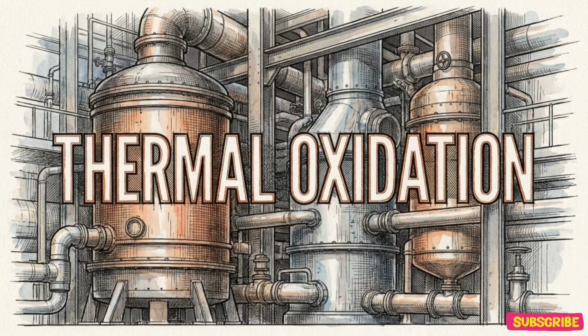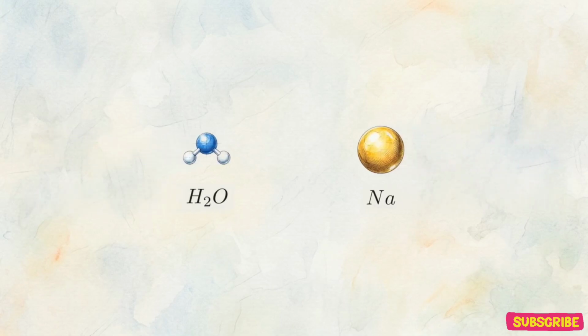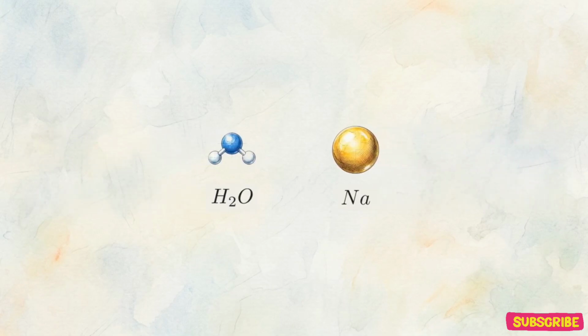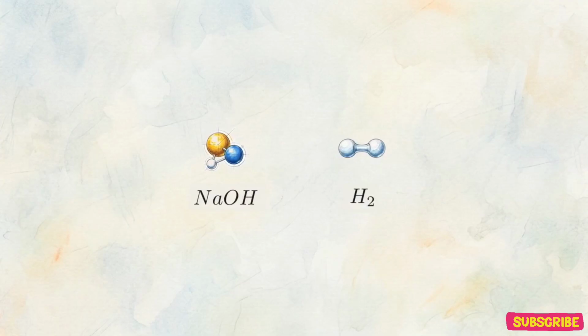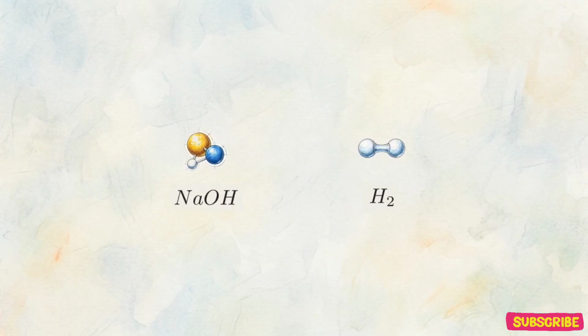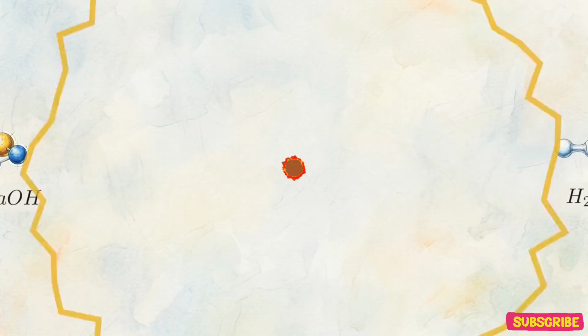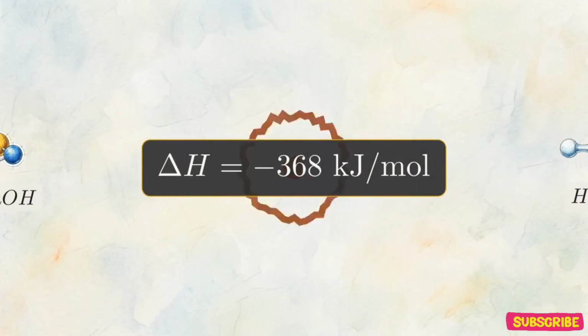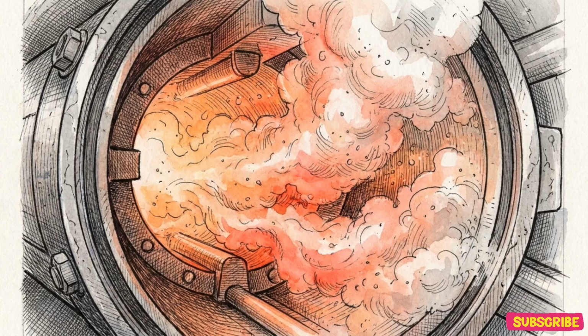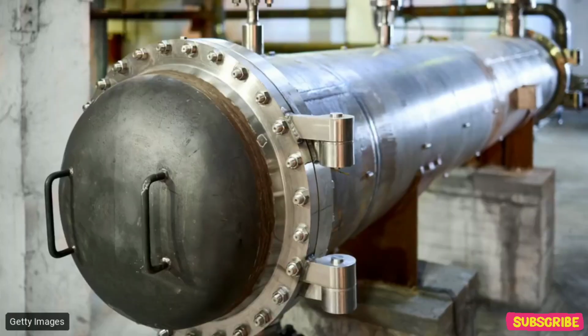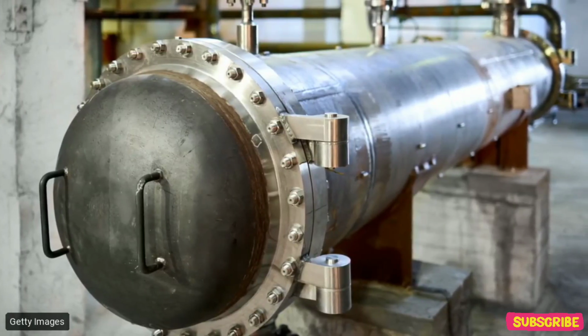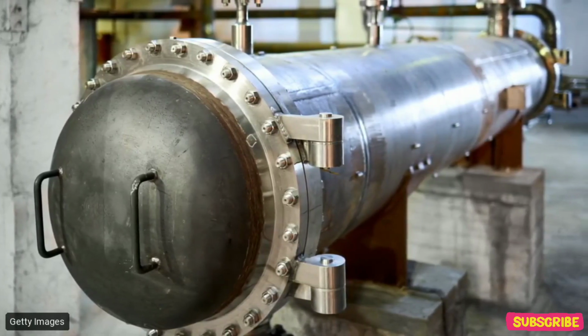What followed was governed by the strict chemistry of exothermic alkali metal kinetics. The exact millisecond the water contacted the 500-degree sodium, it triggered an instantaneous oxidation-reduction reaction, breaking down into sodium hydroxide and hydrogen gas. In mere microseconds, the reaction released an immense amount of thermal energy, totaling negative 368 kilojoules per mole. Alongside this heat, the chemical reaction generated rapidly expanding volumes of flammable hydrogen gas and steam.